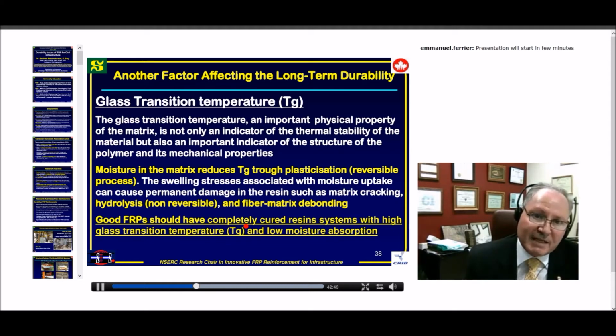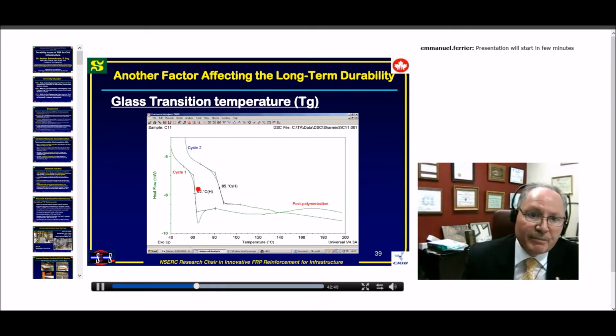As you know, when it's made by hand layup, we also have to consider the thermal property, of course. This is the result from DSC. You have cycle 1 and then cycle 2. Because we did cycle 1, we already heated the polymer resin. So this is all showing that there is post polymerization, as you can see here.